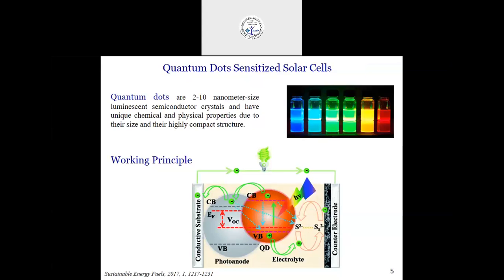So as I said, upon photoexcitation, there is an electron-hole pair generation. The electron marked in green in the conduction band of the quantum dot gets transferred to the conduction band of the large bandgap semiconductor or the photoanode. Now from there, it moves to the conductive substrate and then starts flowing through the external circuit to reach the counter electrode.